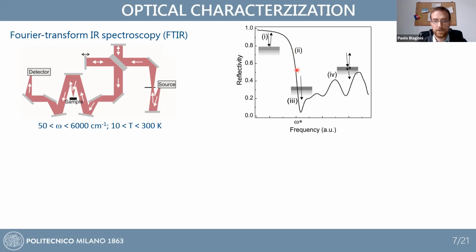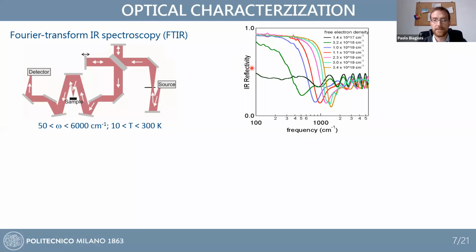And in this change of the dielectric constant, you reach a point where there is a minimum, because basically you become index matched to the surrounding, so you have very high transmissivity. And then at even higher frequencies, you have oscillations, which are Fabry-Perot etaloning inside the film, which is typically in our situation a 1 micrometer thick film. And here you have a dielectric material acting as a Fabry-Perot cavity, basically. And this is indeed what we see when we characterize several films.